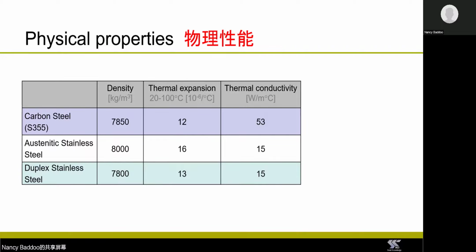Some surprises here when we look at the physical properties due to the different composition of stainless steels. First, the thermal expansion for austenitic stainless steels here is about 30% higher than that for carbon steels. So where you use carbon steel and austenitic stainless steel together, which is quite common really, you need to take account of the effects of this differential thermal expansion.